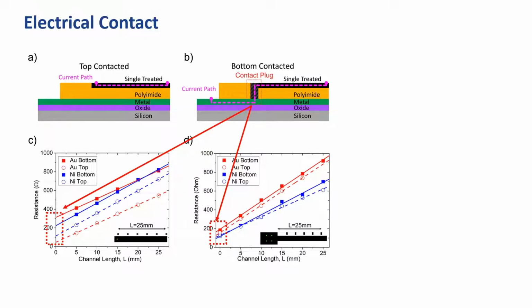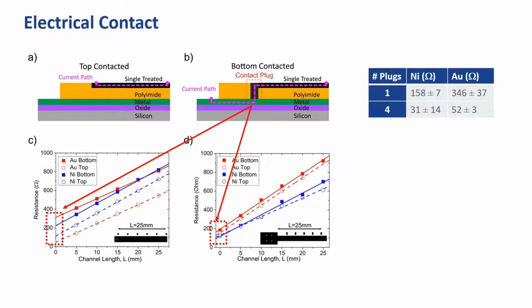On the left we see that for a single contacting plug, the resistance is higher than if the structure was top contacted. On the right we show that using just 4 parallel contact plugs, the access resistance becomes comparable to that of a top contact. The plug access resistance can then be estimated for both the top and bottom contacted structures without the need for patterning the base metal. It is worth noting that while these values are large relative to what would be needed for energy storage, they are comparable to the sheet resistance of laser-induced graphene, making them suitable for sensing applications.